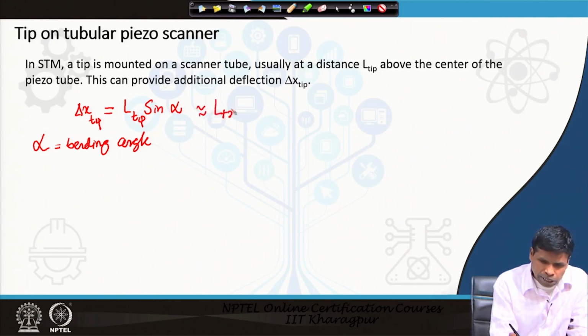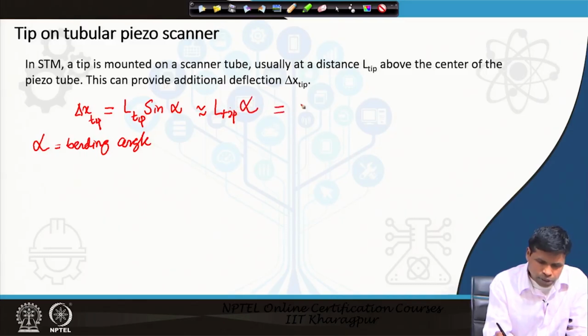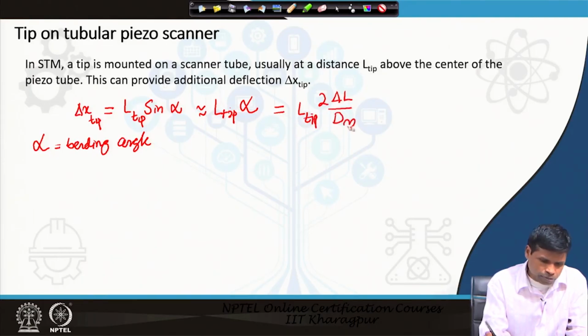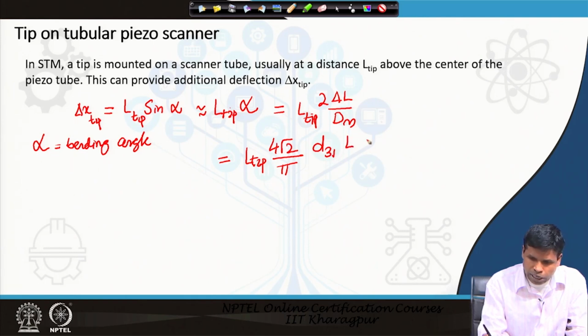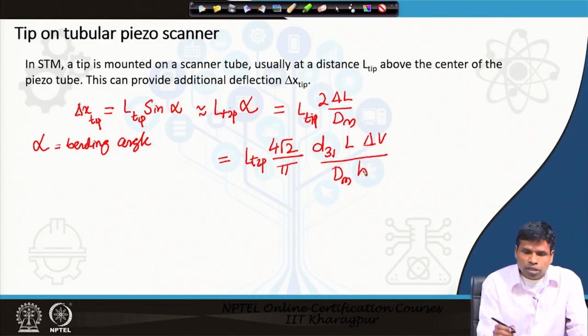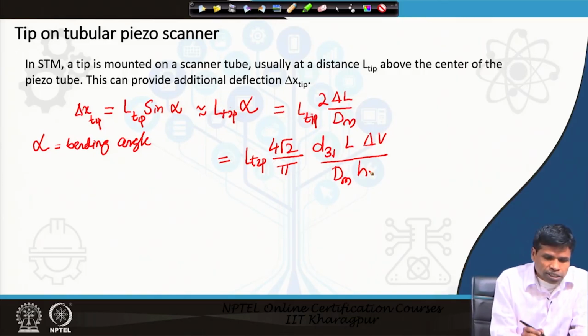Therefore, we can write L tip alpha, which is equal to L tip 2 del L by dm, and which is equal to L tip 4 root 2 divided by pi d31 L del V by dmh. I am not going into the detailed derivation of this equation, directly putting it here, how the del x tip is calculated. This is an additional deflection when we put the tip on the piezoelectric scanner.